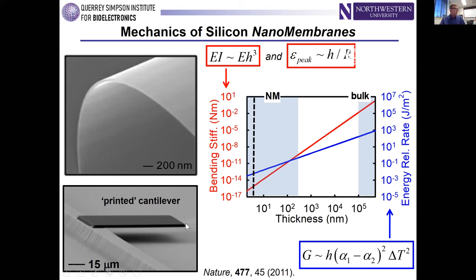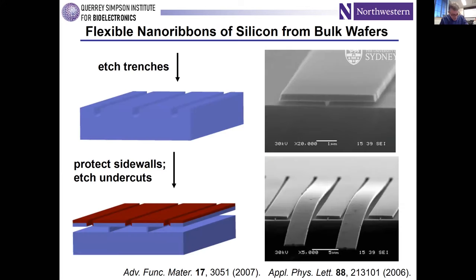That's illustrated qualitatively here in the form of this SEM view of a printed cantilever object of silicon sitting on top of a micromachined ridge on a piece of plastic. There are really no adhesives here. It's just van der Waals forces that keep this in a suspended, cantilevered state. It's because of that strong reduction of the energy release rate parameter G with thickness that allows you to do that. So silicon nanomembranes are interesting because they're very flexible, floppy, and at some level they're sticky. It's very easy to integrate them with similar types of materials. So that's the mechanics, the overall motivation of being interested in semiconductor nanomaterials in this context.